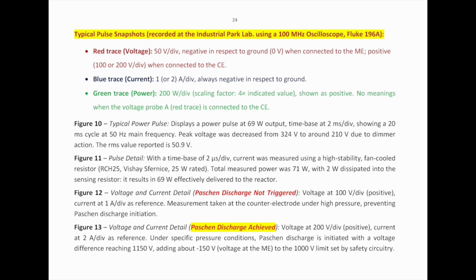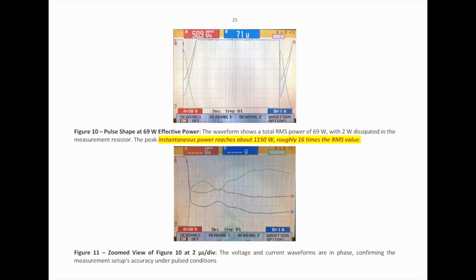Now I show you data. The first one is a typical pulse at low power, now 71 watt. The pulse has a peak current in this experiment of about 6 ampere and voltage about 200. Repetition 50 Hertz, so 20 milliseconds.